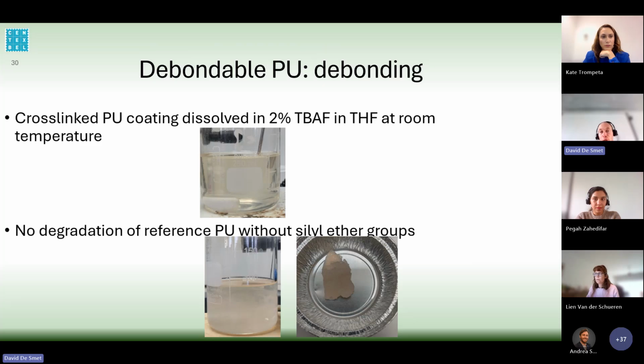Just some pictures of how it looks in real life. The picture above shows you a cross-linked PU coating, which was dissolved in 2% tetrabutylammonium fluoride in a solvent at room temperature. The solvent is necessary, of course, and will depend on the hydrophobicity of your polyurethane. In our case, it's a bio-based polyurethane, which is hydrophobic, so therefore we need a hydrophobic solvent.